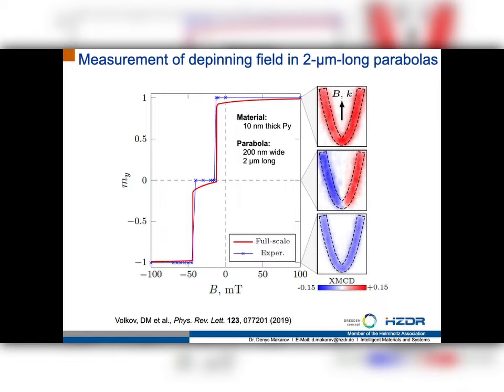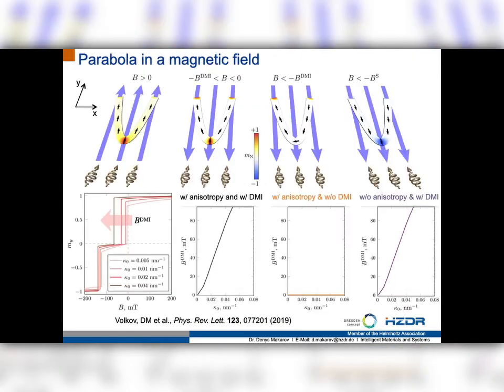As you can see, it's not a very small parabola. You have a 2 micrometer long stripe, 200 nanometer wide, and 10 nanometer thick. It's a symmetric stack. You don't have any Dzyaloshinskii-Moriya interaction which comes from interfaces of this parabola. You can now combine the theoretical, analytical, simulation analysis, and also experiments in order to understand the nature of this first switching field, which you can see here at about, let's say, 20, 30, 40 millitesla. In this case, you can analyze this field as a function of curvature at the apex of the parabola, and you will see that this field scales linearly with curvature, which is exactly what you would expect from the curvature-induced Dzyaloshinskii-Moriya interaction, which comes from the restructuring of exchange interaction due to the curvature in the system.